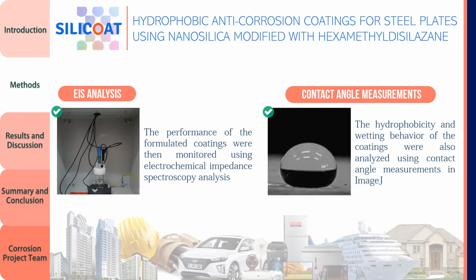Electrochemical impedance spectroscopy was used to determine the total impedance of the coatings. Silver chloride was used as reference electrode, while stainless steel was used as counter electrode. The cell setup shown here was then connected to an impedance analyzer. A software, Nova 2.1.4, was used to analyze the impedance data.